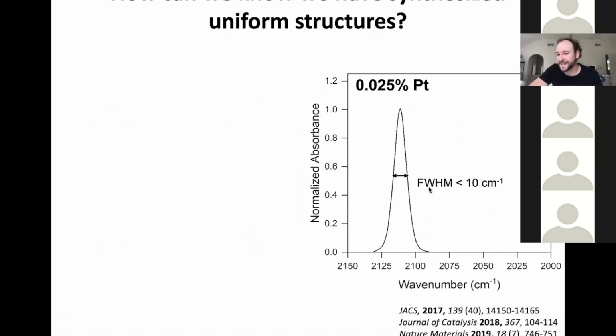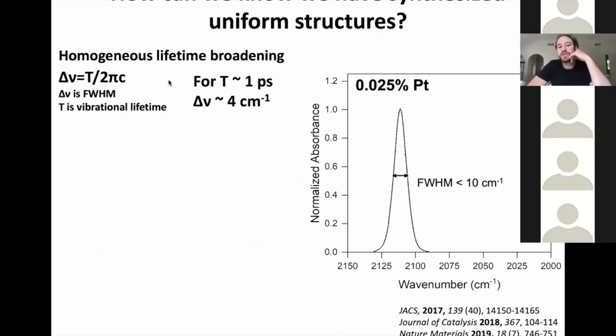So what does that tell us? First you have to consider, in the width of a band in an infrared spectrum of CO bound to a metal, what the homogeneous broadening should be. If you just look at the equations for the homogeneous broadening, it's really just based on the lifetime of a vibrationally excited state. You're absorbing a photon, exciting this CO to an excited vibrational state, and then it's going to decay.